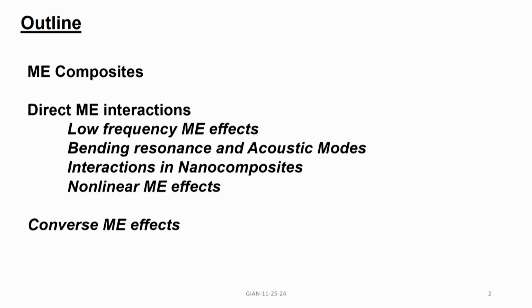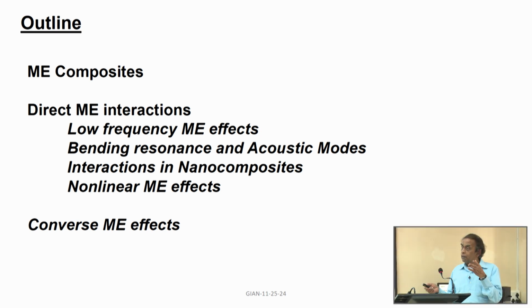So, we will talk about what are the various ways of measuring the direct magnetoelectric effect, which we define as the response of the composite to a magnetic field, the response in terms of changes in the ferroelectric properties. It can be polarization, it can be dielectric constant, or even the ferroelectric domains under a magnetic field.